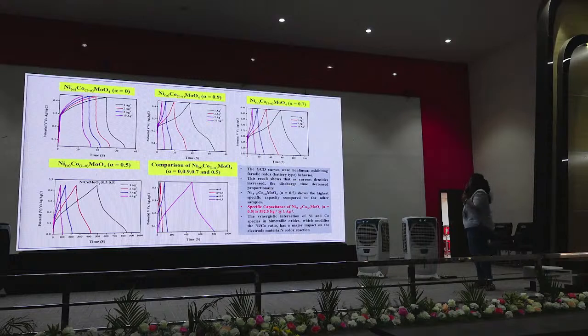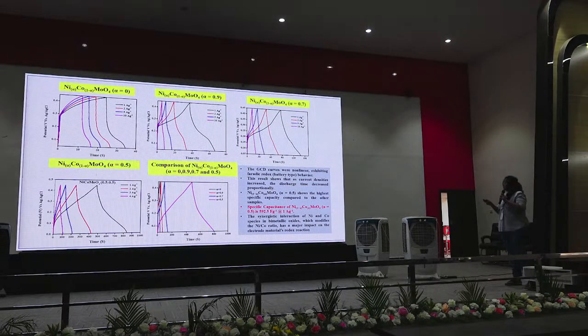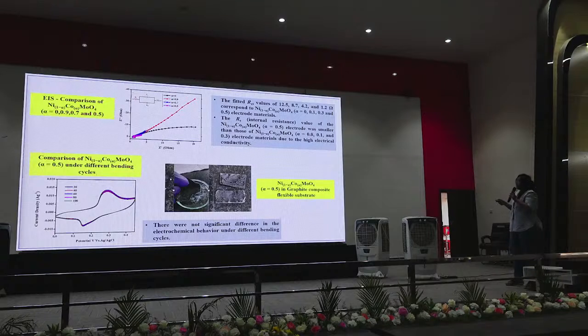We have got around 592.5 Farad per gram at 1 ampere per gram. So these are the studies which I have done. Then comparing the EIS of all the nickel cobalt molybdate samples, specifically on nickel impregnated cobalt molybdate, the nickel cobalt molybdate has the least solution resistance here.